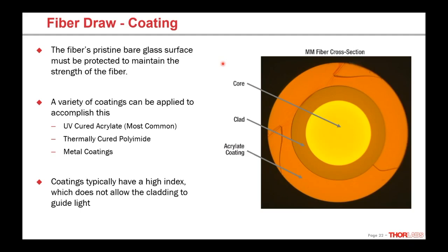Acrylate plastic is the most common coating — flexible, easy to apply, UV-cured. There's also polyimide plastic which is thermally cured and can withstand higher temperatures, useful for applications requiring sterilization or high-temperature environments. Up the food chain there are metal coatings which are expensive but handle very high temperatures. The coating in a standard fiber design also has a very high index relative to the core and cladding. Since cladding to coating goes from low index to high index, you can't get total internal reflection there, meaning the coating strips any light out of the cladding — ensuring the cladding can't guide light, which is necessary for the fiber to function as a waveguide properly.